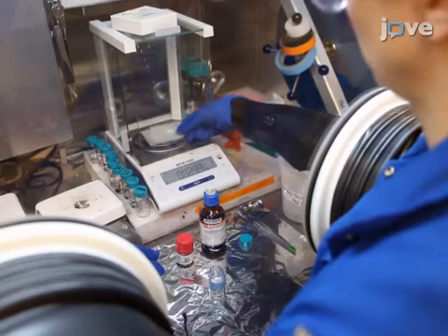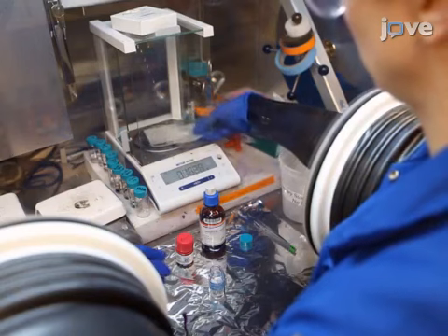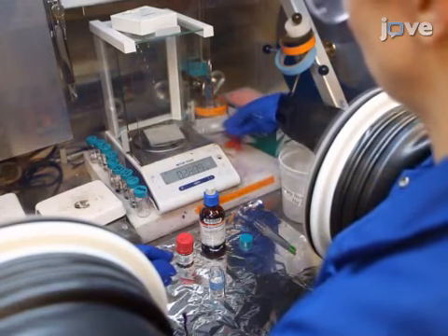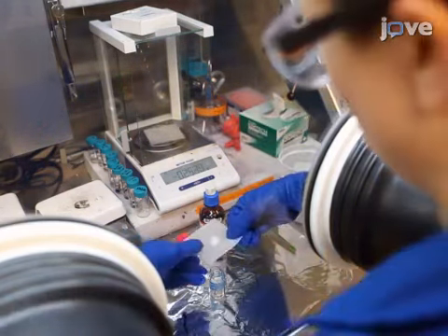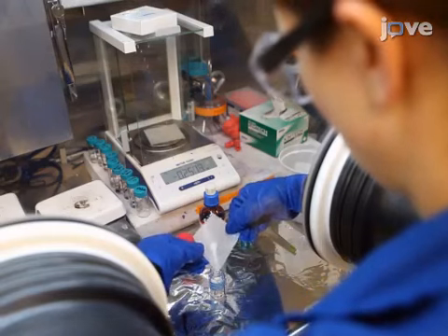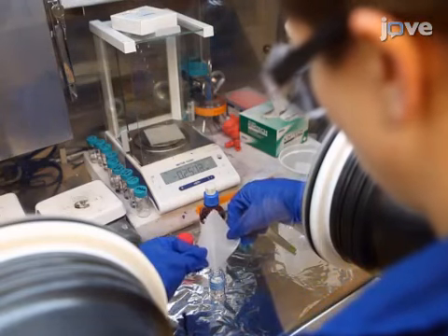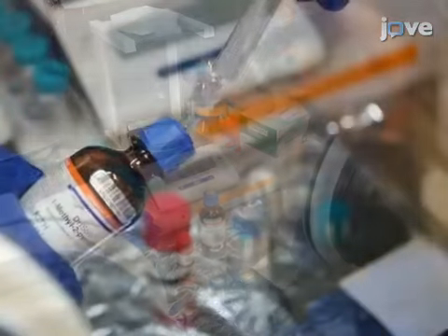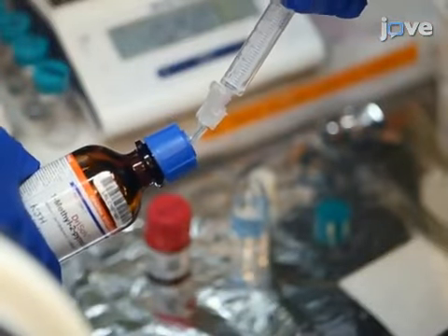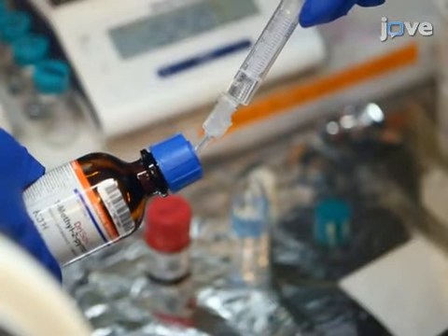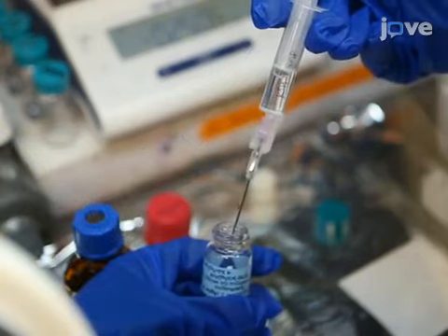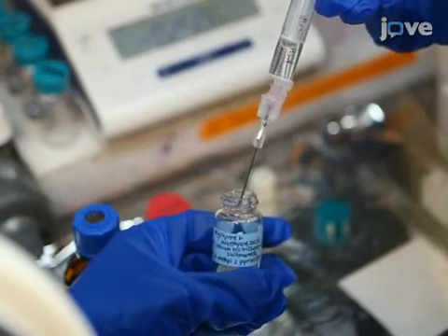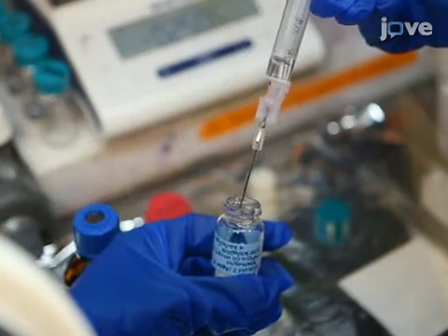Dissolve 0.3 grams of polymer in anhydrous N-methyl-2-pyrrolidone, or NMP, with dry lithium bistrifluoromethane sulfonamide, or LiTFSI, salt. Use an LiTFSI salt to SEO mass ratio of 0.275 and an NMP to SEO mass ratio of 13.13. This quantity of polymer will yield a membrane large enough to make a